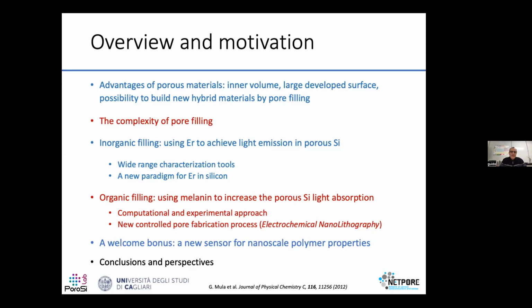However, the filling of the pores can be an extremely challenging task, because when you go to tiny pores, say below 80 nanometers in diameter, you start to have several issues coming from the fact that the pores are not regularly shaped, and that the connection between your material and the pore structure can be complex. I will show you two examples of this.